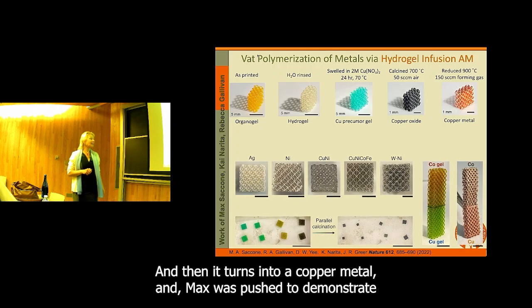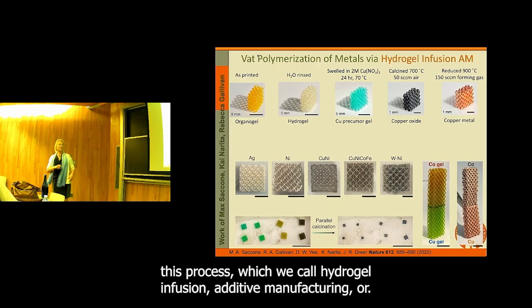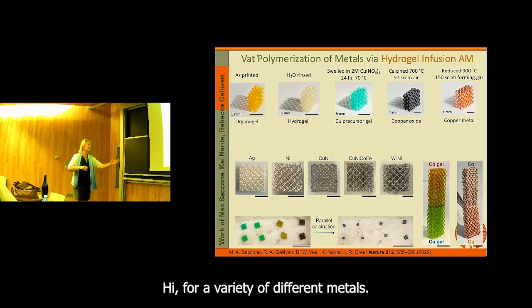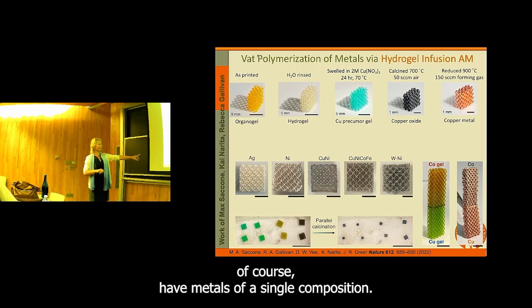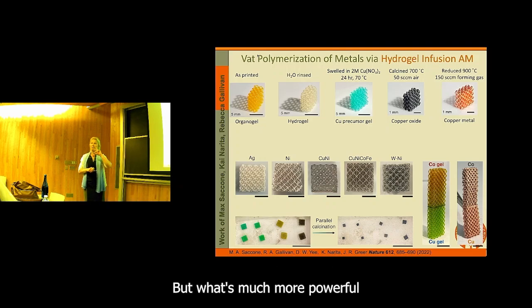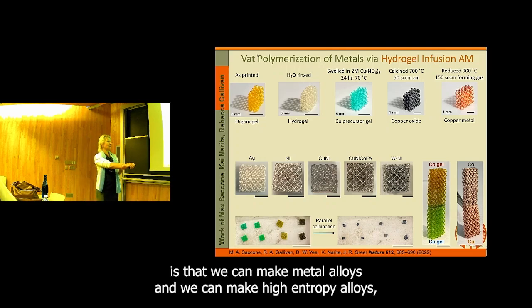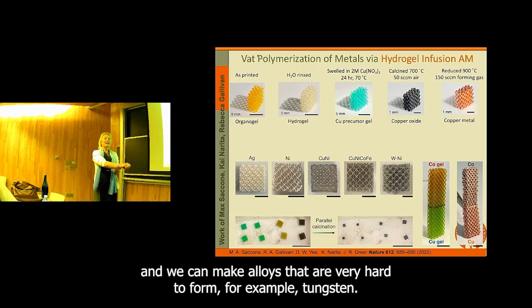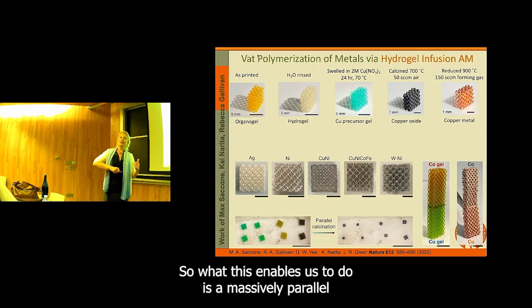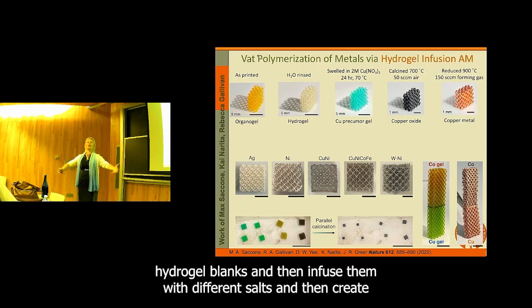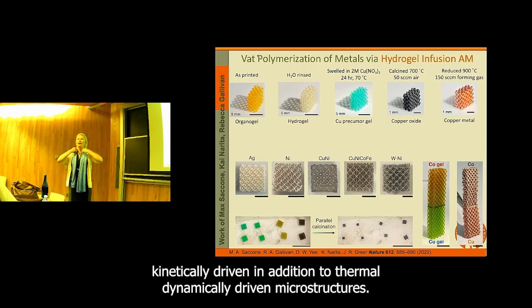And Max was pushed to demonstrate this process, which we coined hydrogel infusion additive manufacturing, or HIAM, for a variety of different metals. And what we're observing is that you can, of course, have metals of a single composition. But what's much more powerful is that we can make metal alloys, and we can make high entropy alloys, and we can make alloys that are very hard to form, for example, tungsten. So what this enables us to do is a massively parallel experimental approach where you can make a lot of hydrogel blanks and then infuse them with different salts and then create kinetically driven, in addition to thermodynamically driven, microstructures.